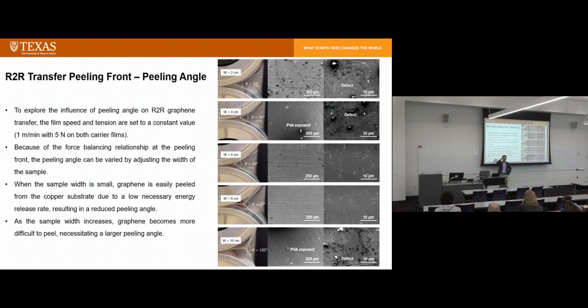But at that time, our machine still could not do it; the force range is not wide enough, so we cannot use large force. So what we did was we chose a lower force, 5 Newton, and then we varied the width of the sample, starting from 2 centimeter to 10 centimeter. And then this will give you different peeling angle, right?